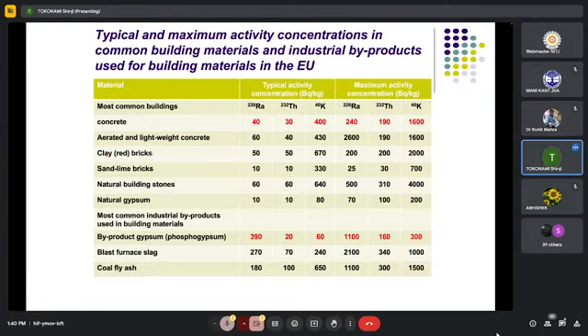Clay bricks, as a typical value: 50 for radium-226, 50 for thorium-232, 670 for potassium-40. As a maximum activity, 200 becquerel per kilogram for radium-226, 200 becquerel per kilogram for thorium-232, and 2,000 becquerel per kilogram for potassium-40.